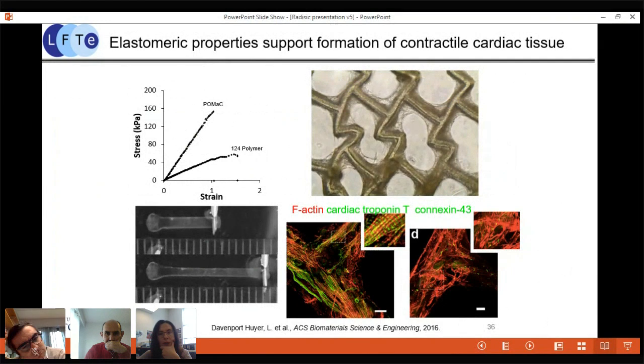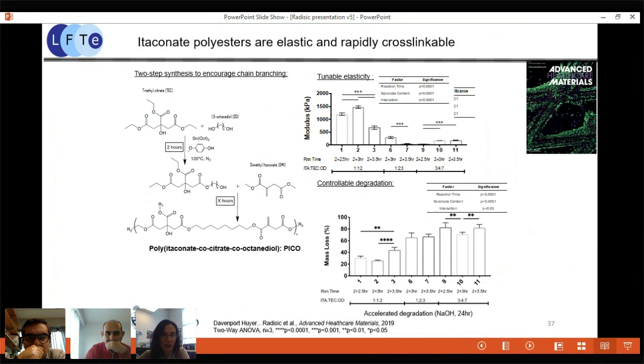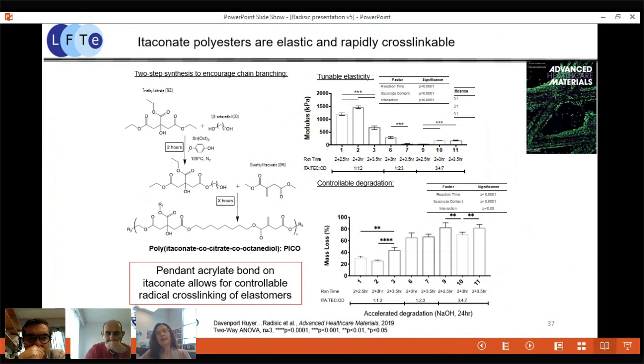And we are also able to grow very nicely oriented cardiac tissues that have well-developed cross striations and that exhibit staining for cardiac gap junction proteins such as connexin 43. In addition to that, another good candidate is itaconate, or itaconic acid. And to further create more versatile polymers, Locke now used a two-step procedure to create these polymers that we called PICO, that contain both itaconic acid and citric acid in them.